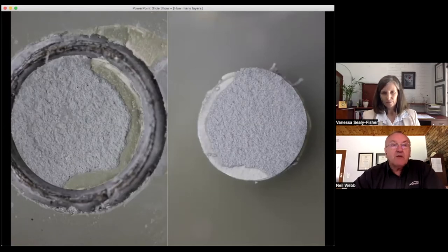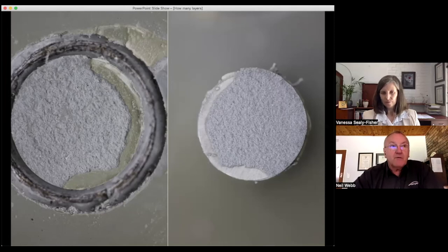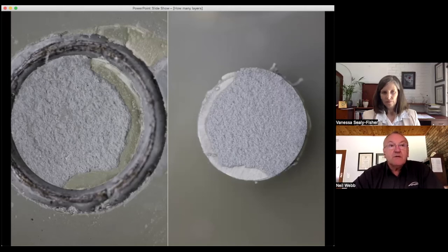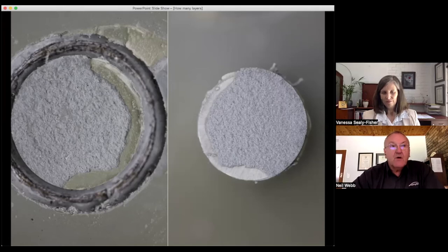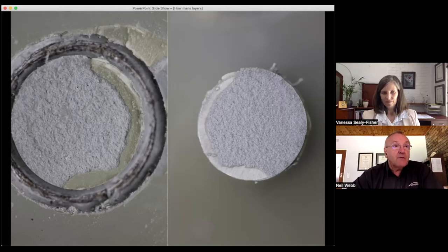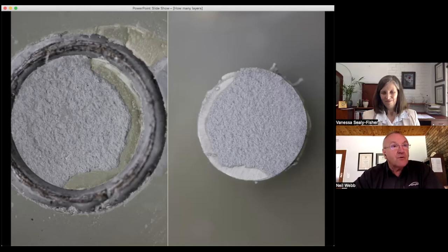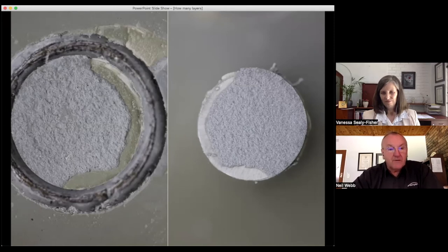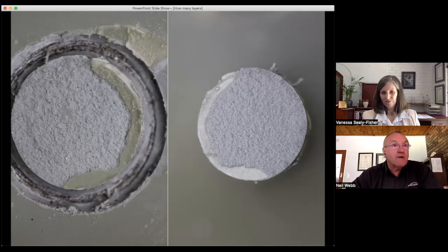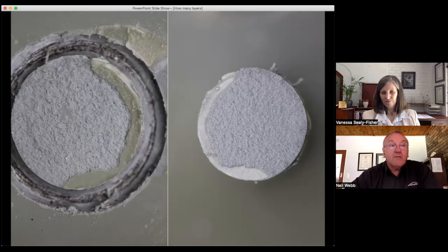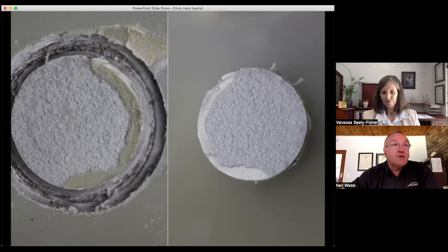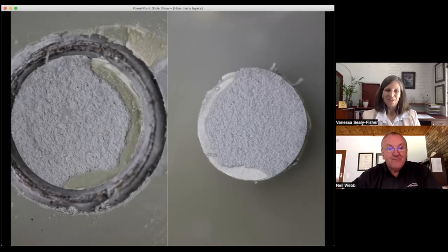The adhesion of polyurethane when correctly mixed, correctly applied, and all the rest is excellent. Here you can see the result of a direct stress adhesion test on polyurethane coating. The polyurethane has failed—in inverted commas, because this is a test to failure. The failure mode is within the polyurethane itself. It hasn't come off the substrate, so this adhesion test is a pass with a tick. When it sticks, it really does stick.